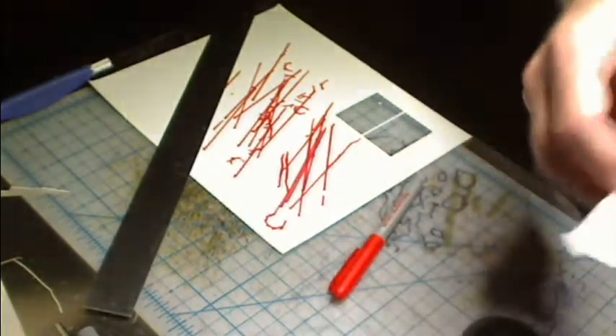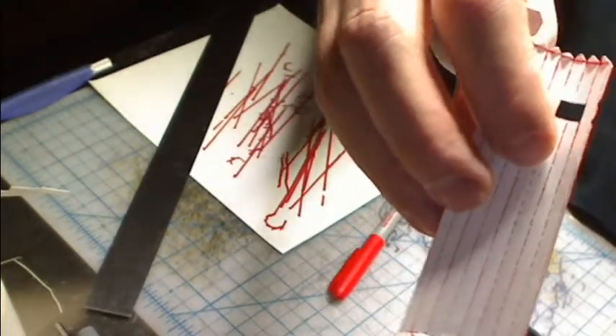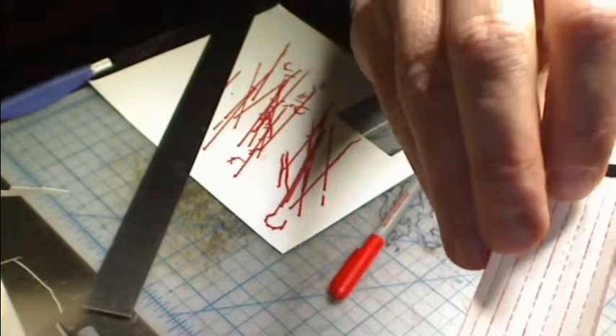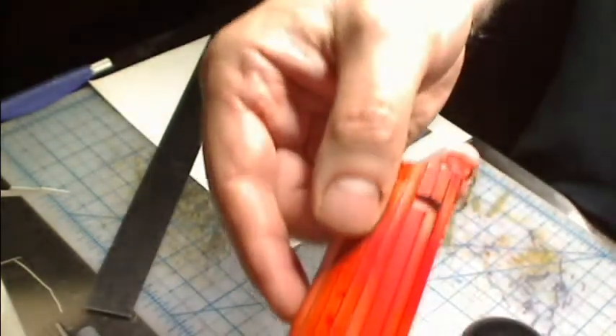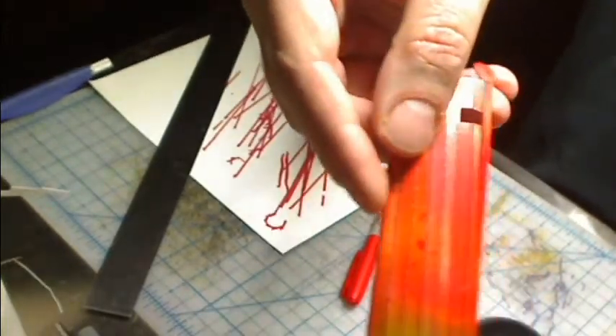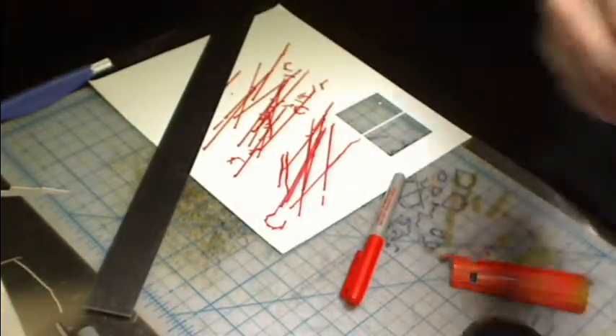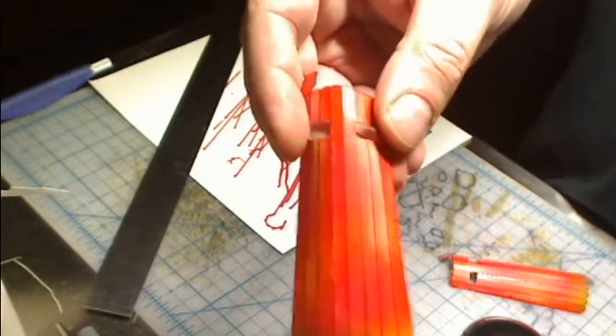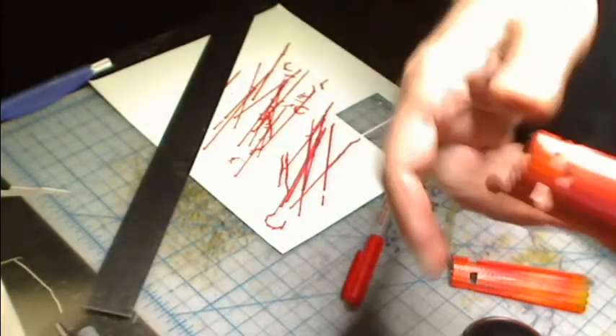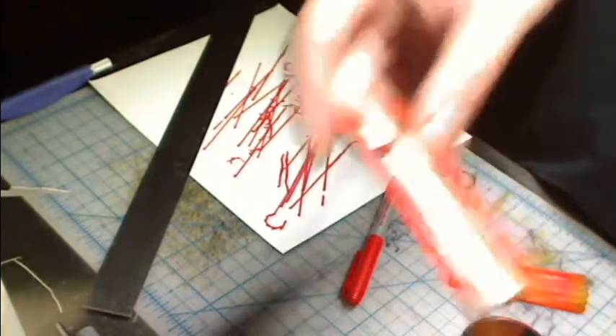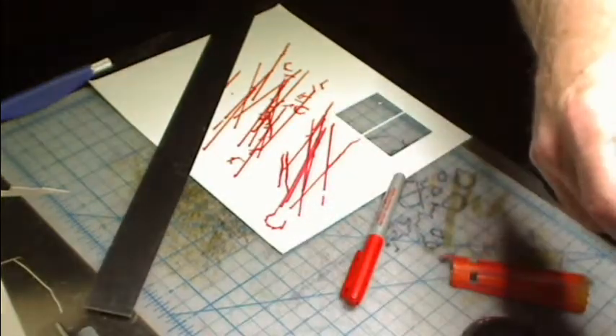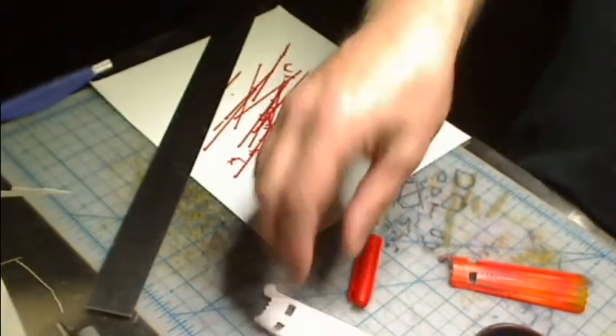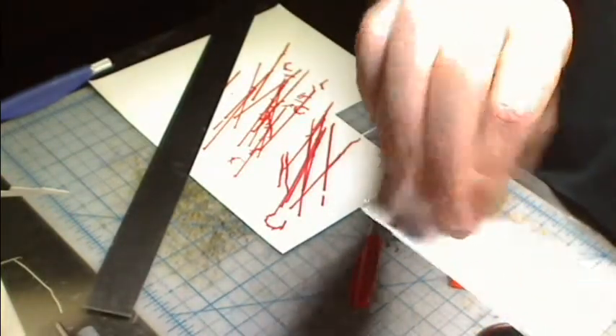I wanted to show something really interesting that I've never seen before. The perforated edging, the red ink of course leaked through the holes and also stained the back. What's really interesting is the hand scored one, you can see the kind of red bumpy edging. Here's the manually scored with a knife tip scoring tool. When you look at the back, the same red ink, no leak there. The stone in between is non-porous, it does not leak. So when considering edging, if you're using this stuff, you can probably use things that you would normally think of as leaking. I normally don't use Sharpies because they bleed too much, but this stuff is basically bleed proof if you don't cut all the way through.